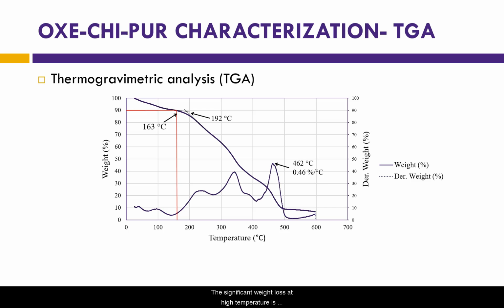The significant weight loss at high temperature is attributable to the disintegration and degradation of the self-healing polymer due to exposure to high temperature. In addition, the derivative weight shows that the highest weight variation occurs at a temperature of around 460 degrees C, which can be identified as a point where self-healing polymer degradation starts.